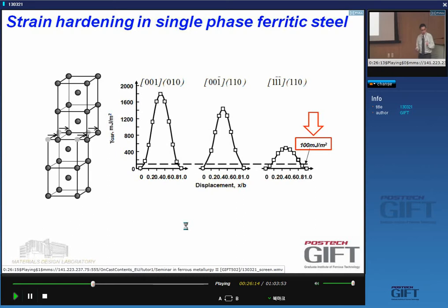What is very important about these dislocations in BCC is that they have gigantic stacking fault energies. These stacking fault energies are so high that we have to use DFT to know what they are. And DFT can help us because you can even get the generalized stacking fault energy. For instance, if you do a shift such as the one I'm showing in the picture and track the change in energy, the top here is what we would call the stacking fault energy. The value is thousands of millijoules per square meter, yes?